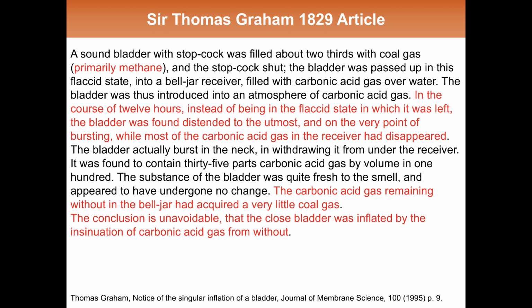And so if you have a balloon that is filled with nitrogen, there is a driving force for oxygen to permeate from the outside air, where the oxygen content is 21%, into the balloon where there's no oxygen initially. There's also a driving force for the nitrogen to permeate from inside the balloon out, but because nitrogen is very slow, the oxygen will permeate into that balloon before the nitrogen can permeate out, and overall the balloon will grow.